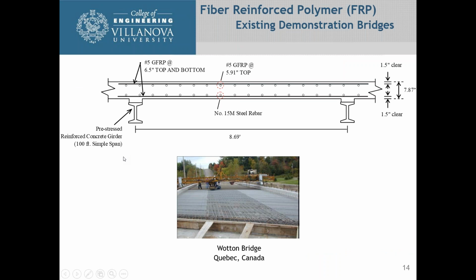Here is a typical cross-section of the GFRP bridge. You can see you've got two girders, and in this case they're pre-stressed girders. You've got your concrete deck, which is approximately 8 inches, with 1.5 inches clear on the top, 1.5 inches clear on the bottom. The transverse bars are number 5 GFRPs at 6.5-inch centers top and bottom. On the top, we're using number 5s at approximately 6-inch centers. And then on the bottom, for the longitudinal direction, they're still using number 15 metric steel reinforcing in the longitudinal direction.